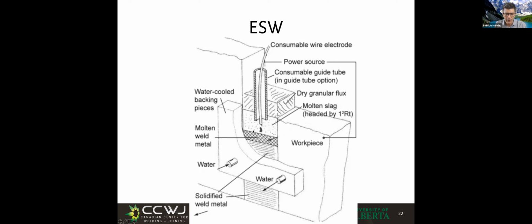And there is no arc here. Typically, the fluxes are high in fluorides, for example, calcium fluoride. And one characteristic of fluoride type fluxes is that when they are molten, they are electrically conductive. So instead of having an arc, what you have is a flow of current that goes through the molten slag, and the droplet falls across.